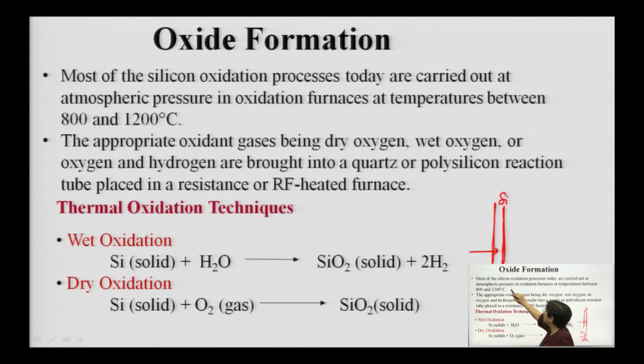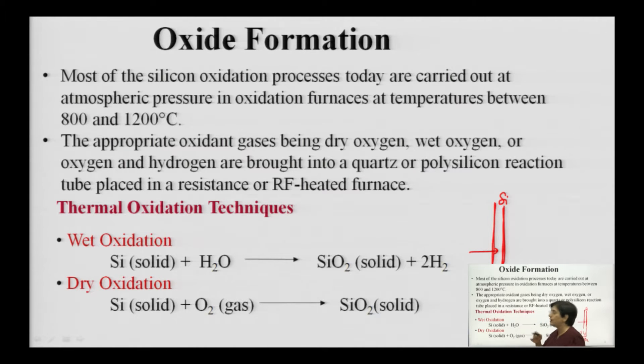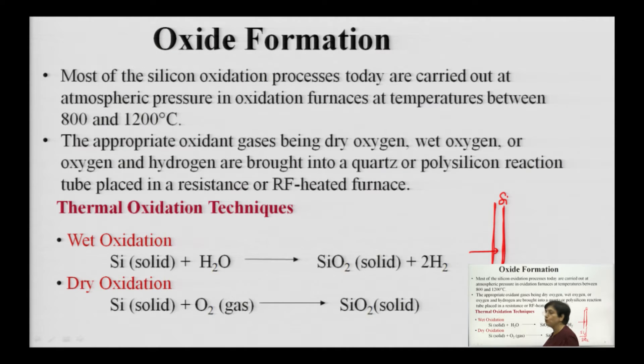The most recommended process is thermal oxidation, carried out at atmospheric pressure and temperatures between 800 to 1200 degrees centigrade. Since silicon's melting point is above 1400°C, there is no harm to the substrate at these temperatures. Appropriate oxidizing species are made to flow onto the surface. Initially, nitrogen is purged for cleaning the wafer, and then the oxidizing species are made to flow over the wafers and the oxidation process is carried out.